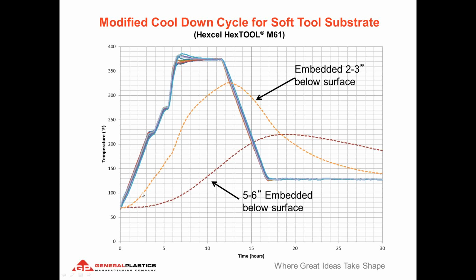Now, since the foam is so insulative, say embedded just 2 to 3 inches below the surface of the foam, it comes nowhere near the maximum temperature of that cure cycle. And some matrix resins will gel at temperatures below their maximum as well. And so that's where the CTE compensations come into play. Because the foam doesn't really grow at the same rate that the temperature ramp up is showing, we need to compensate for a lower CTE value to make sure that the calculations are correct and you don't overcompensate for the foam.